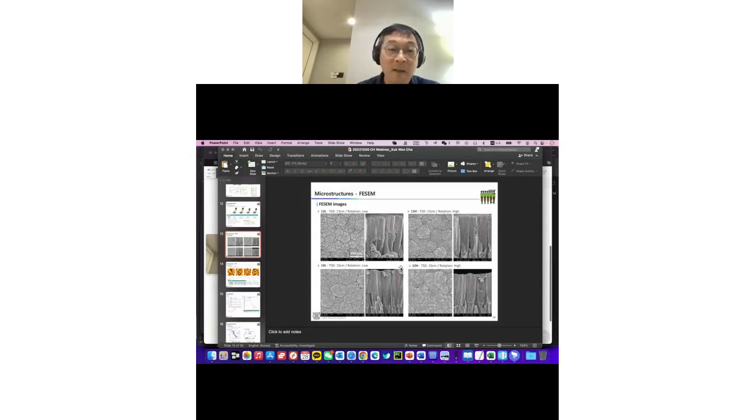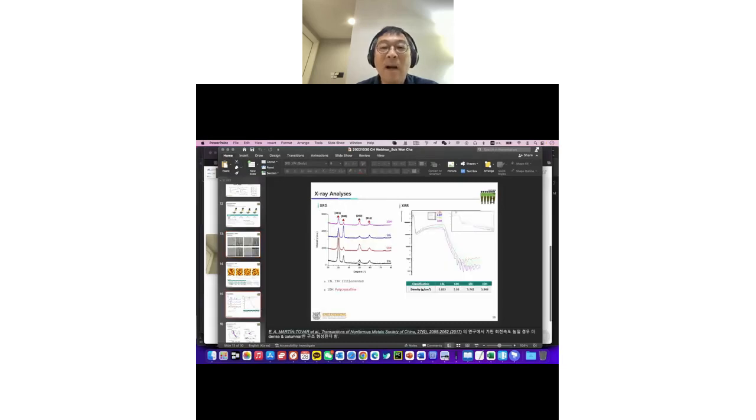I didn't mention it in my talk, but when you have higher power or a short distance, the sticking coefficient is low, but the speed of the particle is large. What we guess is that with a higher speed, which means a short distance, the higher energy bombardment can help the formation of the crystallinity.